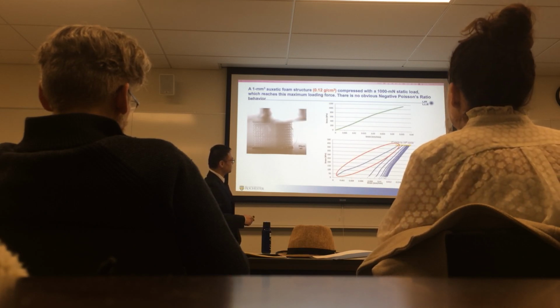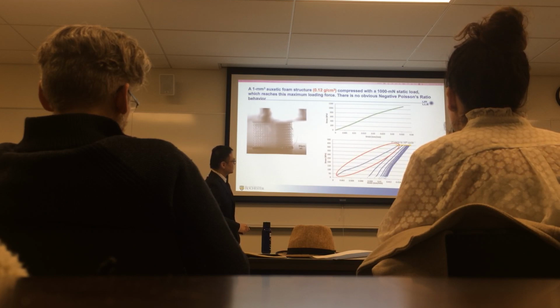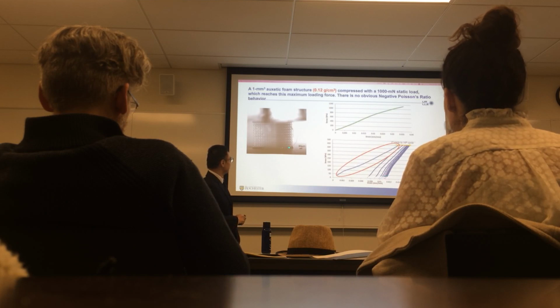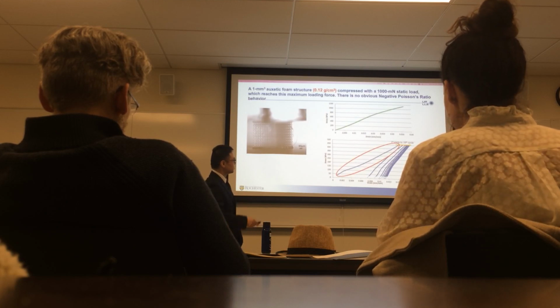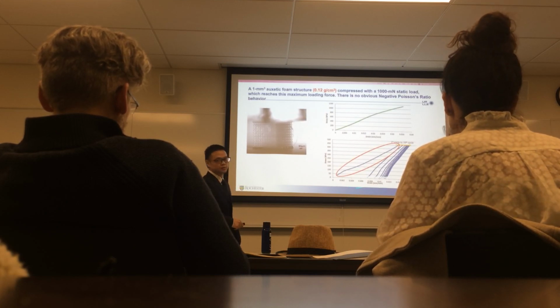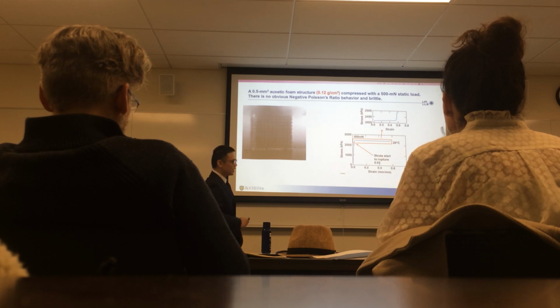During the compression test, we compressed the foam structure several times, but we found that the first cycle has lower values than the rest. We think the gap between the equipment and the samples may cause these low values. So in the rest of our experiments, we will run the compression test several times and ignore the first values. After the preliminary test, we shrank the foam structure to half cubic millimeters.